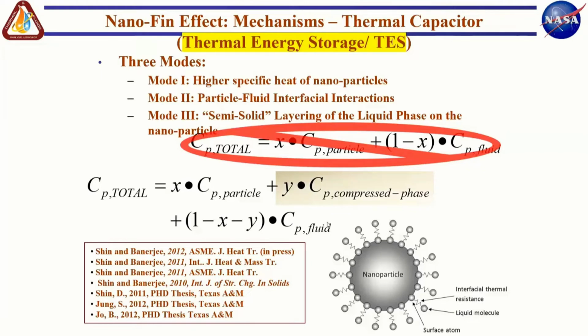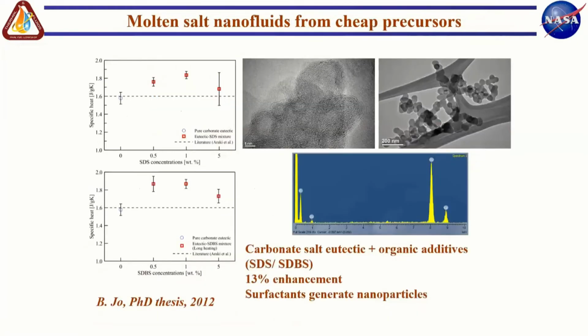And what we realize is that this compressed layer that forms around the nanoparticle is the capacitor. That's the one that is storing heat, and that's what is giving you the heat capacity enhancement. Now, we had an accidental discovery where we found that you don't need to add nanoparticles. If you add surfactants and heat it, the surfactants carbonize and give you carbon onions. And we found that as you keep increasing the concentration of the surfactants, the heat capacity keeps increasing until it hits an optimum, and then the nanoparticles start agglomerating and there is a decrease in the heat capacity.